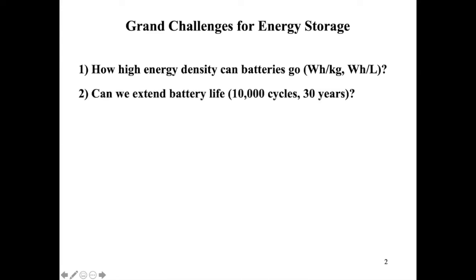The next is, can we extend the battery cycle life even longer, like 10,000 cycles, 30 years together? Certainly you could see some of the batteries probably reaching 5,000, might even 10,000, but you need to think about the constraint as well. Can I keep the same energy density? Certainly now the LFP, LTO combination can give you very long cycle life, but you cut the energy density by half. Also remember that. Can we maintain the energy density while having very long cycle life? Then many materials and chemistry issues start to jump out.